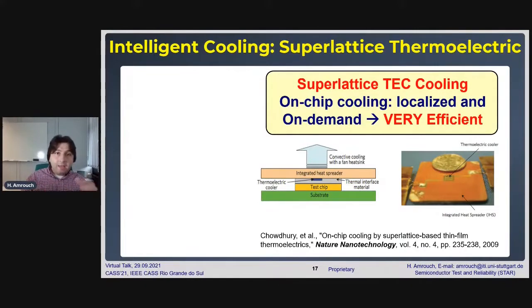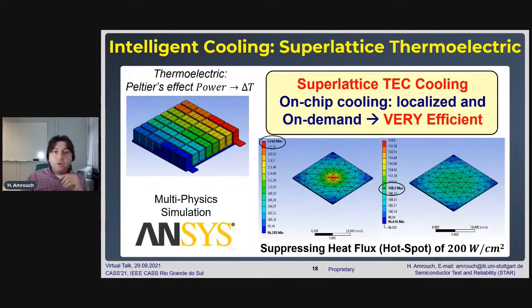In this case, we have done this analysis for the thermoelectric device located on top of the thermal hotspot. We can see here how we are able to suppress the temperature of the hotspot, and it goes down from the critical temperature of around 124 all the way down to around 108. That shows the effectiveness of the superlattice thermoelectric device in cooling a localized hotspot. In this analysis, we have used multi-physics simulations, and in this example, we were able to suppress even a thermal hotspot of around 200 watts per square centimeter.